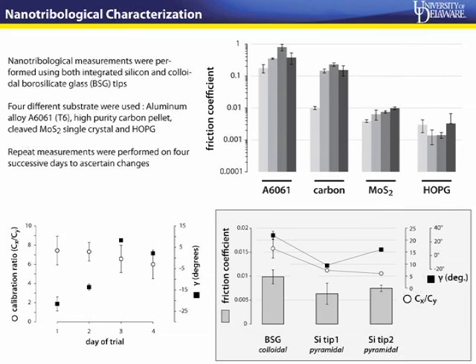This graph represents 4 consecutive days of measurements, so shades of gray tell you the day number. As you can see, there is a trend in friction coefficient between the 4 days, which we think is largely because of variations in the environment, the humidity, because these samples were stored in lab air, so there was possibly a gradual uptake of moisture. But what's interesting to note is that each of the bars represents the average and the standard deviation of 10 measurements within a single day on that particular sample.